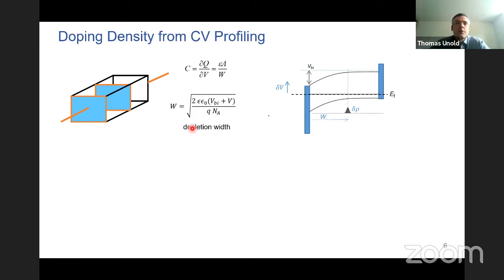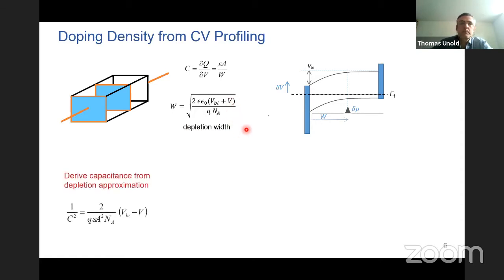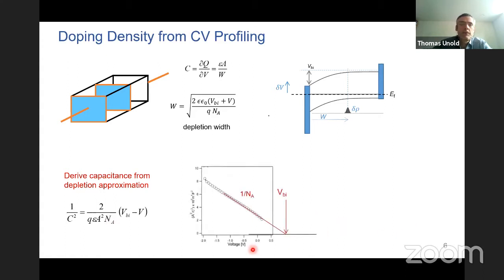And then what is also important to know is there's a simple equation for the depletion width. You can calculate it from this depletion approximation. And from that, since you know that this is the capacitance, you can derive a simple formula for the capacitance as a function of the applied voltage. And it turns out if you plot 1/C² versus voltage, then you get the inverse slope of the doping density. So if you do that, here's 1/C² over voltage plotted, you should expect this straight line here. And so the inverse slope, 1 over the slope, is the acceptor density, and you can even get the built-in potential. So that looks very nice.